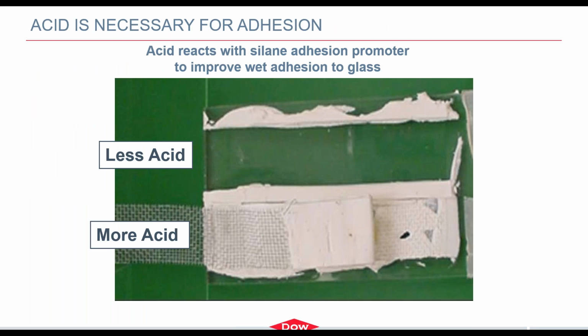So, two examples from that previous list. Sometimes acid in the backbone is very necessary for adhesion, specifically wet adhesion to glass as part of the ASTM C920 specification, in that the acid can react with the silane adhesion promoter that's in the formulation. This is an example on top where the polymer has less acid in the backbone and you get complete adhesive failure. Whereas in this sealant below, there was more acid in the polymer backbone, and we got this cohesion splitting of the sealant, which is the desirable mechanism of failure.